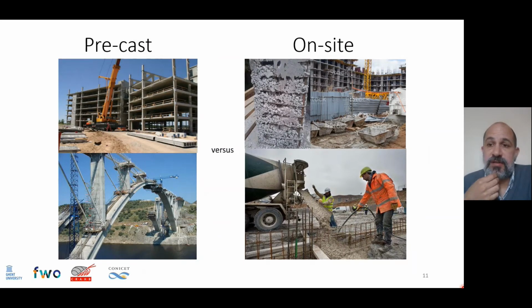Another strategy that is very much suitable for the Latin American market is the increase in the proportion of the precast industry in the construction. So when we compare precast to on-site concrete, the first thing we notice is that we need more clinker in cement and we need more cement in concrete to produce precast elements. And this is due to the need of faster strength development than concrete on site. But on the other hand, the systematization of the production and the quality control